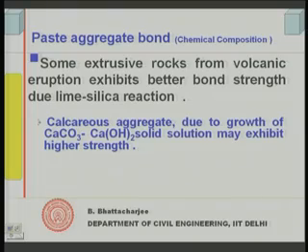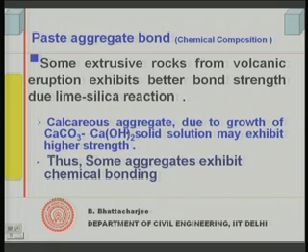Some other calcareous aggregates have been reported to show some sort of chemical bonding, namely calcium carbonate reacting with the calcium hydroxide and forming solid solution, and they have shown some higher strength. But by and large, aggregates are supposed to be inert and do not show chemical bond. Thus, some aggregates exhibit chemical bonding, not all. But mainly it is the physical and mechanical bonding which are important.